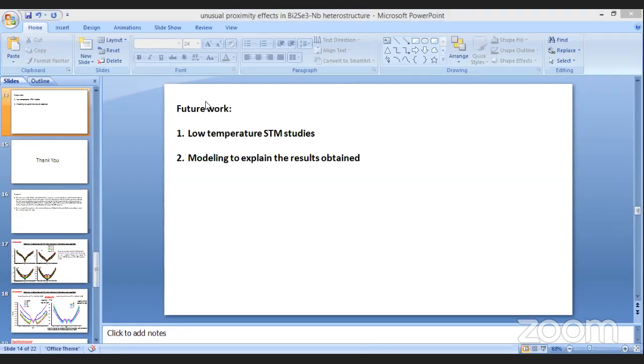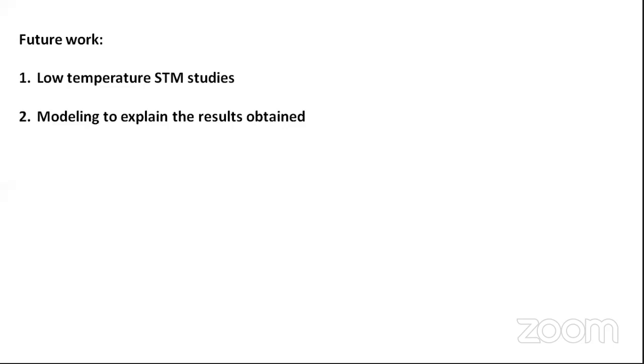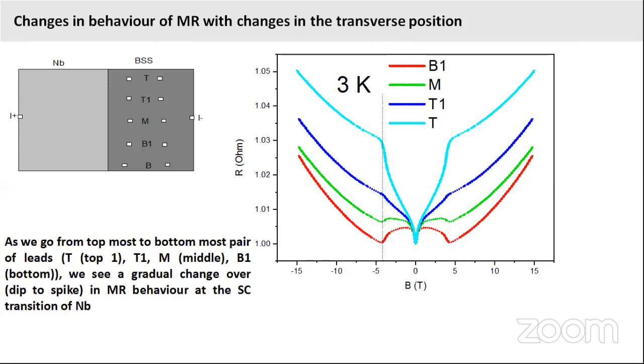I would like to ask a short question related to the contacts, because I assume they are going to play a crucial role in the measurements, because your resistance is also quite small. So what is the contact material in this case on the superconductor and on the niobium? Copper wires with silver paint. So it's not that you have deposited the contacts and then used wire bonding or something. We thought of doing that, but it's essentially the same thing. So in both cases, these are copper wires, and then a silver paste which you have dropped on top of that and dried it. Yeah. Okay.